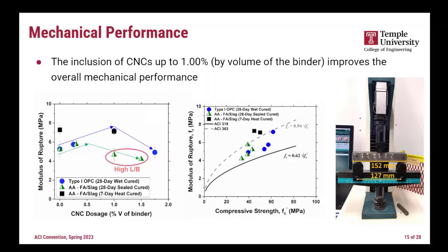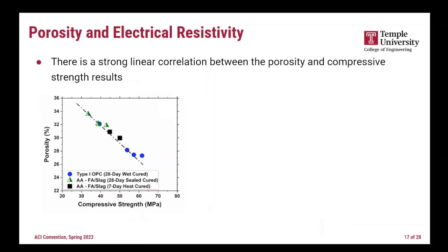This is the compressive strength versus the flexural MOR, right? And we compare with the ACI equation. So you can see the heat-cured alkali activated is a very ductile system, even if it performed as a high-performance concrete. And that's a CNC mix we tested. Even CNC mix with 0.1%, it showed very promising results, 30 to 40% increase in the modulus of rupture.